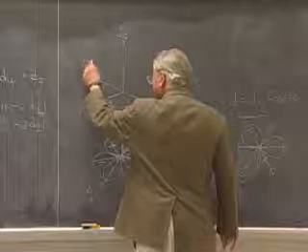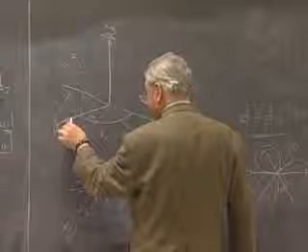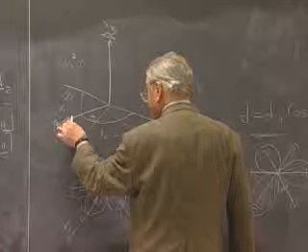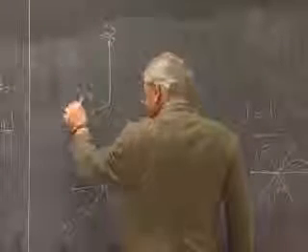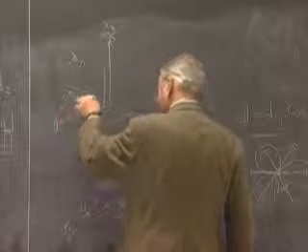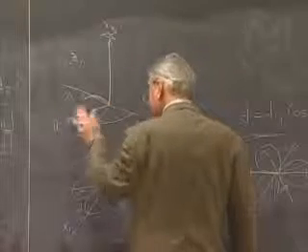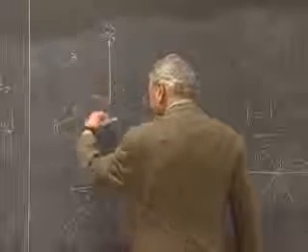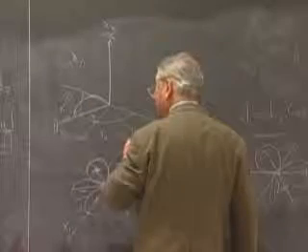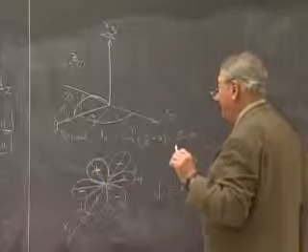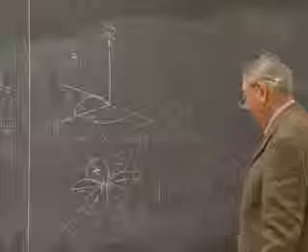So this then goes as cosine cubed of phi, which is a lobe that starts out at plus 1, and then because it's cosine cubed, this dies out very, very rapidly. So these lobes are very flat in the x1, x3 plane, and die out very rapidly as the cube of phi, where phi is the angle between the twofold axis and x3.